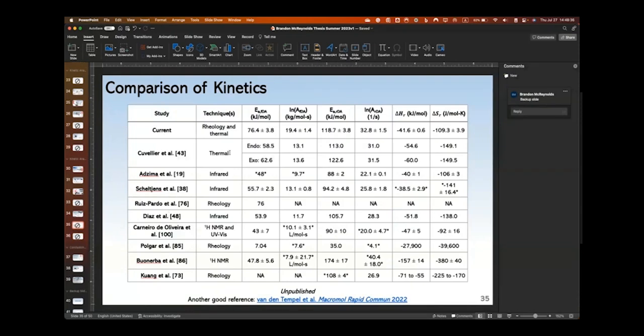Okay, so yeah, this top line is my data, and then the other ones are example studies I've pulled from. So, the enthalpy of reaction, I got about -40. Other studies have gone between like -30 to -60. For the entropy, I got about -110. Other studies have gone between about maybe -90 to -150.